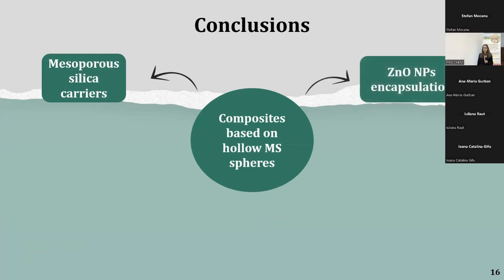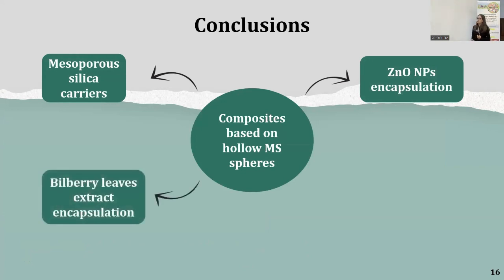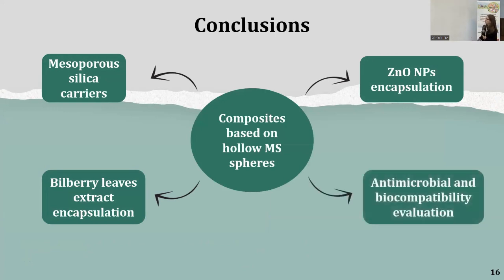Methods of encapsulating zinc oxide nanoparticles in the hollow silica spheres were developed. Both pristine and zinc-modified silica spheres were used as supports for bilberry leaves extract to obtain extract-loaded materials. And finally, the antimicrobial and biological evaluation showed that these materials are suitable for topical applications.